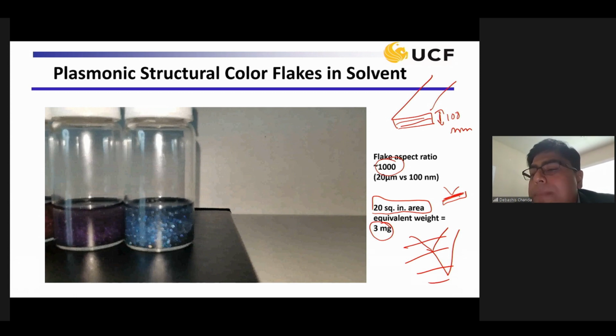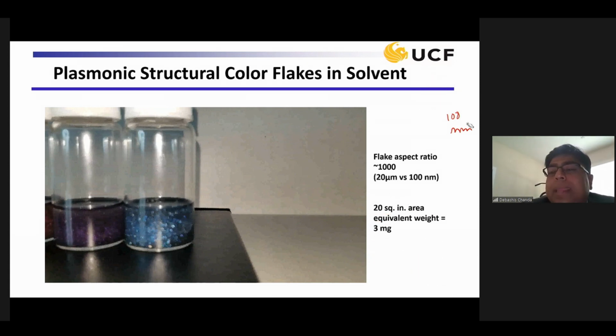That means it does not matter whether you keep putting more flakes. Light will not see that. So if you can coat an extremely thin layer, we can really make a nanoscale film without compromising the color depth. So the Beer-Lambert law, e to the power minus alpha d, does not apply here. We could make extremely lightweight, ultra thin paint, and I'll show some.